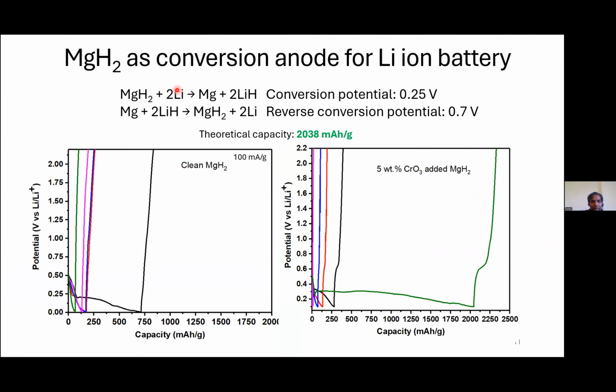Before that, we need to go through this. The forward conversion reaction is expected at a potential around 0.25 volts, and the reverse conversion is expected for this material at 0.7 volts. And if you get a deflection in your curve at these potential regions, then you will be very happy, when you are using clean magnesium hydride, even a 100% pure sample.